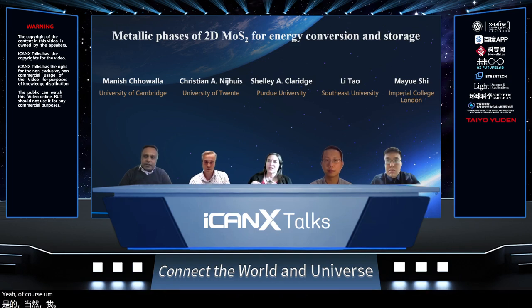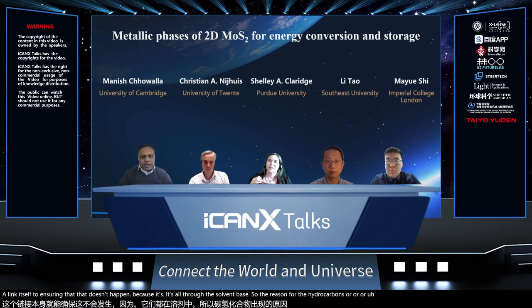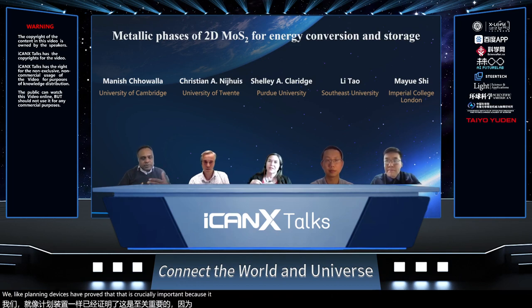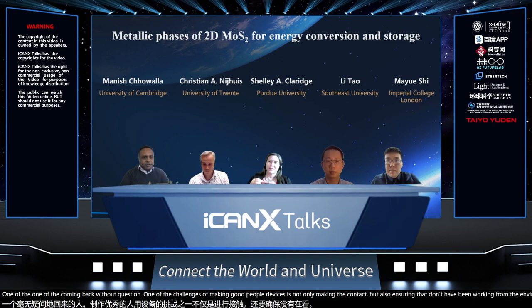Yeah, of course. The main challenge with all of these 2D materials is that oftentimes you have junk on the surface which has thickness values that are two to three times the thickness of the material itself. So that is a huge problem. The chemical exfoliation process lends itself to ensuring that that doesn't happen, because it's all solvent based, so there aren't hydrocarbons that junk up the surface. For electronic devices, of course, that is crucially important, because coming back to Tao's question, one of the challenges of making good P-type devices is not only making good contacts, but also ensuring that you don't have doping from the environment, the substrate, and the adsorbates.